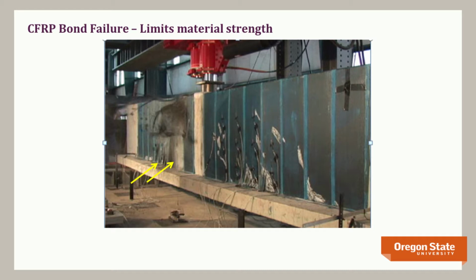We've done a lot of work with carbon fiber as well. And you can see this is a screenshot at the point of failure, and you can see those yellow arrows are pointing to the point where you're essentially ripping off the carbon fiber from the surface. These wet layups really are bonding to the worst part of your concrete, which is the skin, right, that's subjected to all kinds of freeze-thaw exposure. It's mostly made up of paste, even though you do some surface grinding.